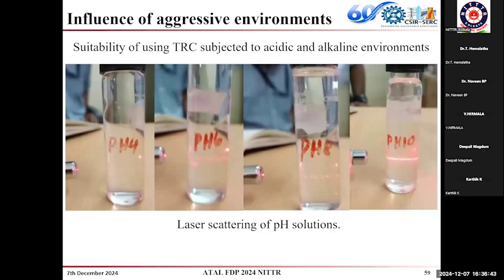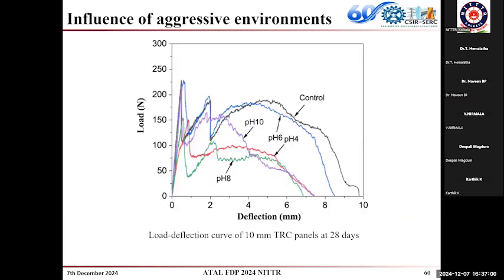So these are some of the studies we have carried out, to see how it behaves in different environments. This is a textile reinforced concrete specimen cured in different pH solutions, and the pH solutions were tested for any dissolved materials, whether anything has leached out of the textile reinforced concrete. And we have carried out the deflection test with various thicknesses of the specimen. This is subjected to different exposure conditions, like different pH conditions, acidic and alkaline, because the matrix is rich. If you see the composition of textile reinforced concrete, the composition is very rich, so the fibers are not supposed to be affected by the different exposure conditions.